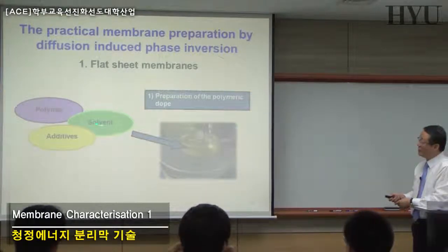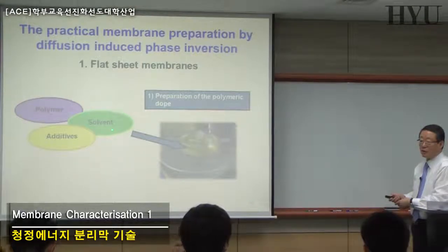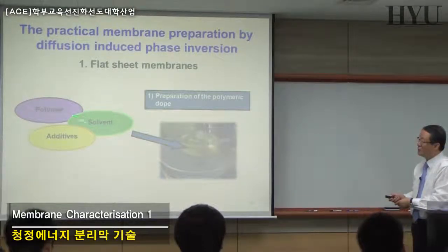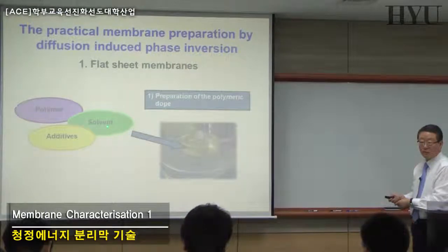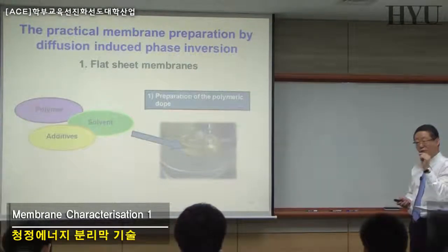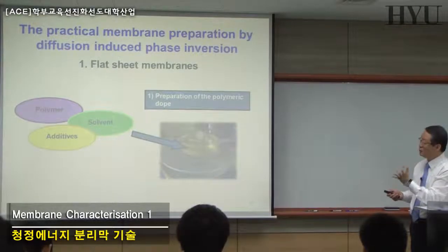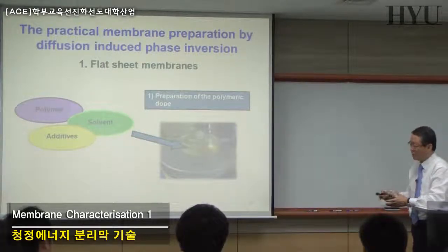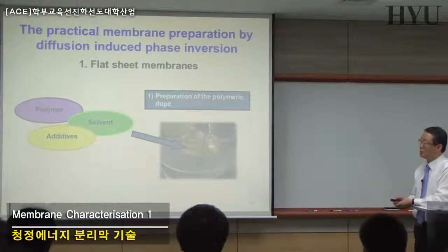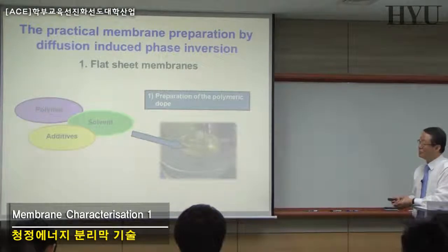Okay, solvent should be the good solvent. Good solvent should have the similar solubility parameter between the polymer and the solvent. So solubility parameter difference should be minimum in the 2D solubility parameter approach. Whereas if you add the additive as the bad solvent or the poor solvent, then the solubility parameter might be different, and it might be larger between the poor solvent and the polymer than the polymer and the good solvent.